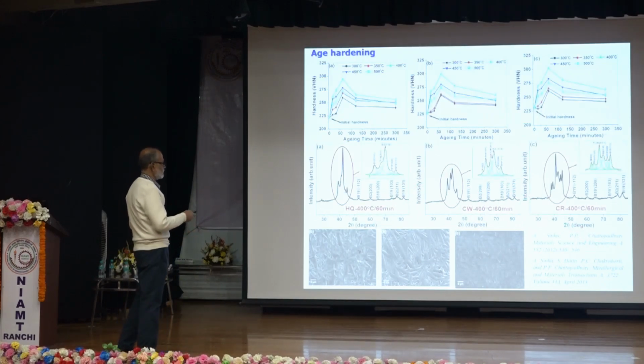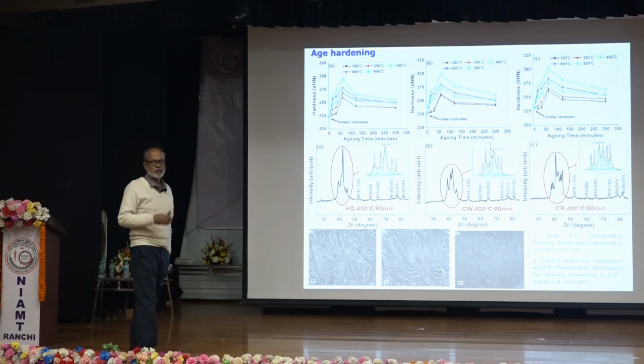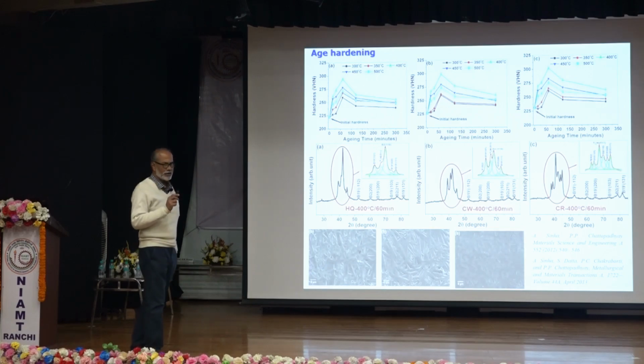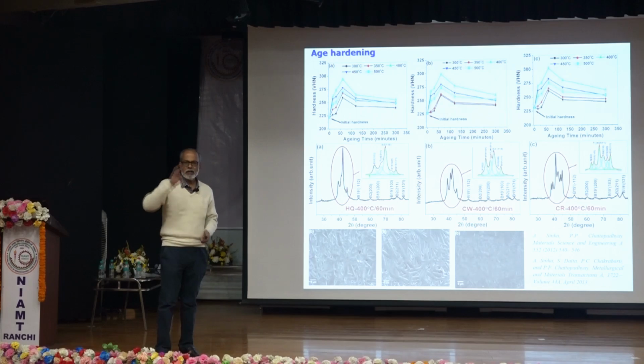We also conducted aging, right? And we observed that at a certain temperature, 400 degrees centigrade, and for a certain time, we have maximum hardness. So we considered these because our intention was to increase the critical resolved shear stress. Our intention was to defer the plastic deformation so that we have a large region of recoverable strain. So taking that, we conducted the experiments, we did XRD, and here we found the formation of precipitate phase. So there occurs precipitation, and it is Ti2Ni phase. Now you can imagine what effects can be there. As there is deformation,